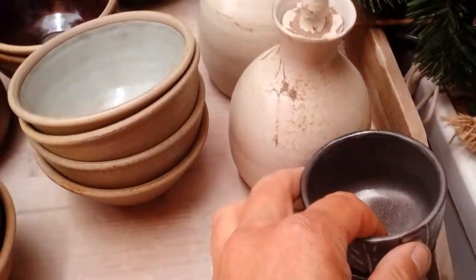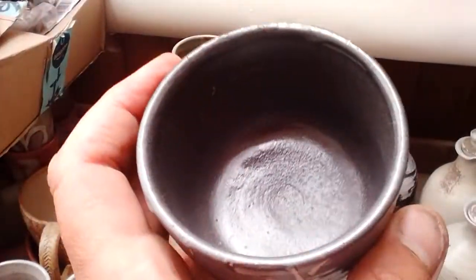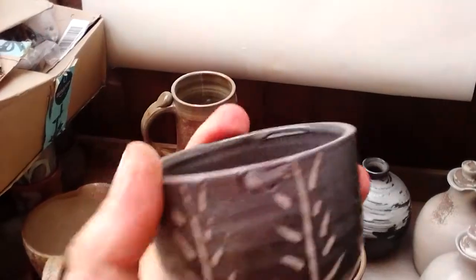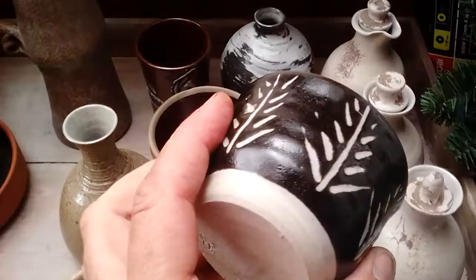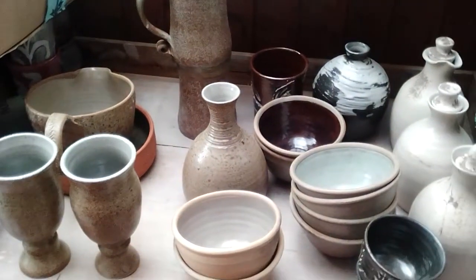These were put in raw and they've crawled a little bit, but they're just for candle wax anyway. I just wanted to fill a couple of spaces up, so I'll quickly re-glaze those. Bye for now.